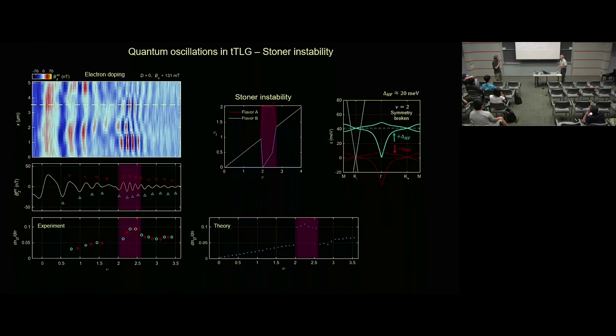And you can quantify it quite well. How big is the gap at 2? We get about plus or minus 25 millivolts. Do you do these measurements on the same sample, or do you have many samples? This twisted tri-layer graphene, we measured 3 samples. What I showed you is one of them. We have data on 2 more.